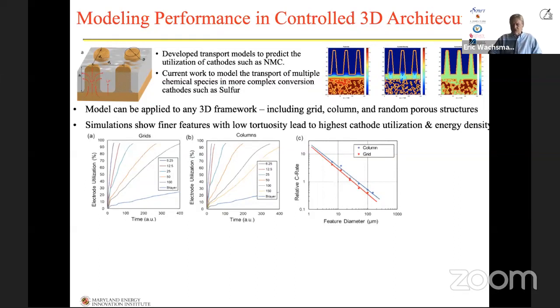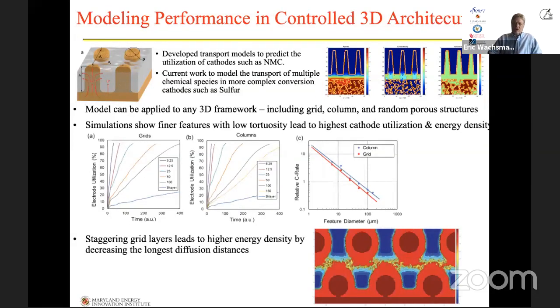And that's what's shown on the figure to the right, which is the relative C rate. C rate for a battery is the charge rate, how fast you can charge and discharge it, versus the feature diameter on these grids and column structures. The other aspect for columns, for grids, is where do you place them? Do they directly overlap each other, or do you have them staggered? And what we're seeing from the modeling results is you actually want to have the grid structures staggered, so that as you have these different lines, one line overlaps the pore on the layer below.